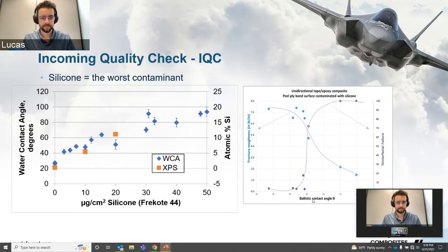If you're familiar with water break testing, above 60 degrees, water break always fails. Below 40 degrees, water break always passes. 40 to 60, sometimes it passes, sometimes it fails. It just doesn't really have the accuracy to give you that kind of gray zone. That gray zone is super important, right? Because that's usually what's happening in processes: you're operating in this gray zone. And that's why once in a while things fall apart and nobody can figure out why.